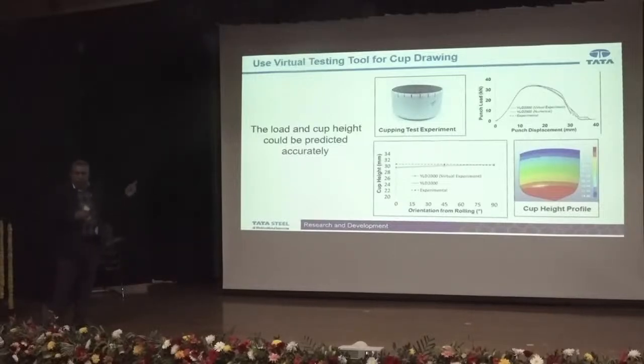And then we used the same to do a real life simulation. So we made a cup using the same steel for which we did all those experiments, and we measured the punch load when we were drawing this cup, and also we measured the earring height. Basically the cup height shows the amount of earring happening in this cup. And you can see prediction versus experiment using different models. One is YLD, the Barlat criteria, where all the coefficients were calculated using real physical experiments. And in the other, all the coefficients were calculated using virtual experiments, meaning the crystal plasticity based model which we had developed in-house. You can see the prediction is quite good, both for the load as well as for the cup height. So there is hardly any difference. So we are confident that such an approach can also be used going forward for testing, etc.